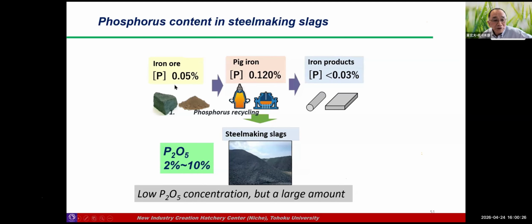Very interestingly, initially the very high grade iron ore has a phosphorus concentration of only about 0.05. Then through the blast furnace, in the hot metal, the phosphorus increases to 0.12%. And through the steelmaking process, all the phosphorus is moved into the steelmaking slag, and the P2O5 in the steelmaking slag increases to 2% to 10%. So from nearly 0 to about 2%, a huge concentration takes place.